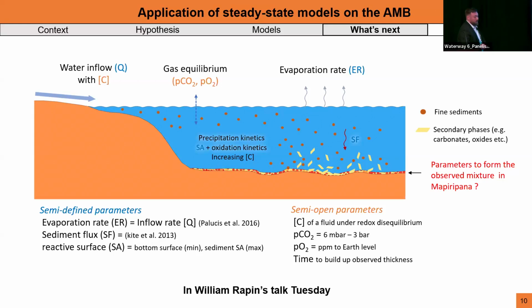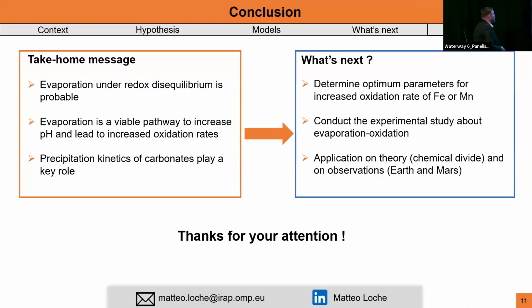that we want to do this model and that we really need to consider this kinetic disequilibrium at the start, because if we don't, you would determine wrong parameters, basically. So my take-home message is that evaporation under redox disequilibrium is more than likely on Mars. You will have weathering of your watershed, transport of your elements in the water, and it will be evaporated, probably with still iron and manganese ongoing oxidation, with an ongoing oxidation by oxygen, because Mars is oxidizing, right, in some conditions, because we find oxides.